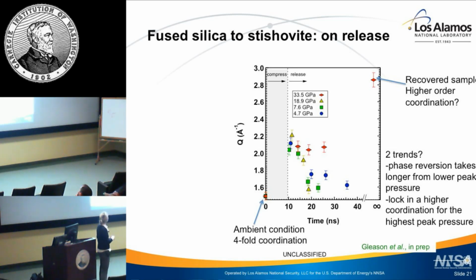So the lower pressure set sort of comes back down to something that's more like our ambient condition, 4-fold coordinated, but the higher pressure one does a sort of uptick. So could we be seeing 2 trends here? Could we be seeing a quenching in of a high density amorphous state? Perhaps. This also leads us to think about, in the real rock scenario at an impact site, we only pick up 2% by volume stishovite. A very small volume is actually crystalline stishovite. There's quite a bit of what's called diaplectic glass or shocked glass. So the pathway, how that shocked glass transforms, maybe this provides insight on that.